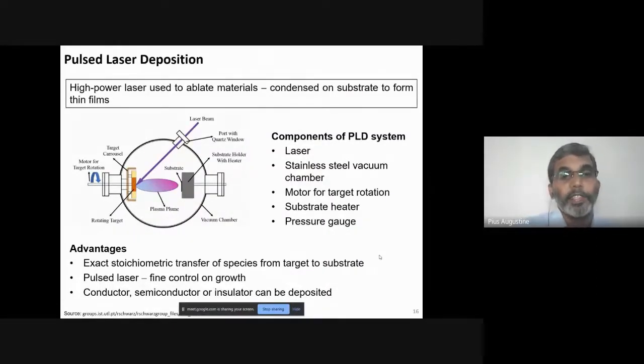So here is a chamber, and in that chamber we can control the pressure using a pump. We can reduce the pressure inside. We can evacuate to a very low pressure of around 10 to the power minus 6 millibar. Then the laser, which is a clean energy, comes from outside through a narrow window opening, and this highly focused, high energy laser will reach the target. We call it the target; something like our paracetamol tablets will be there, made of the material.